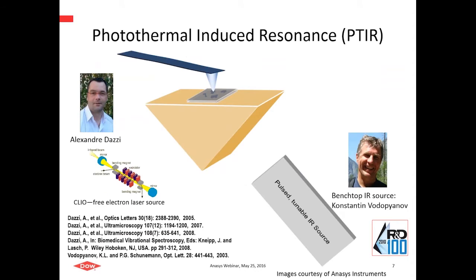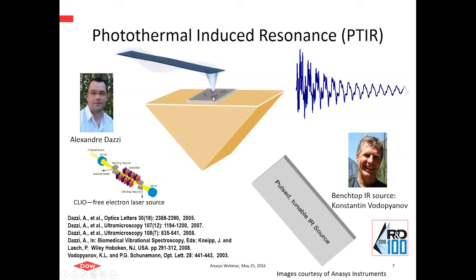Craig gave you a nice snapshot of how the technique works. This is an early cartoon I had from him during our collaboration. I'll run this really quickly. In this case, this is the original implementation of the technique using a single bounce ATR crystal, and in this case, the pulsed mid-IR radiation came from below the sample and was reflected internally into the crystal, excited the sample. Where there was absorption, we got the resonance as shown before, and the ring down shown up here